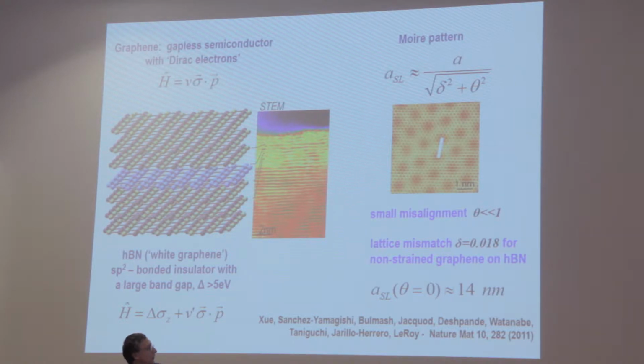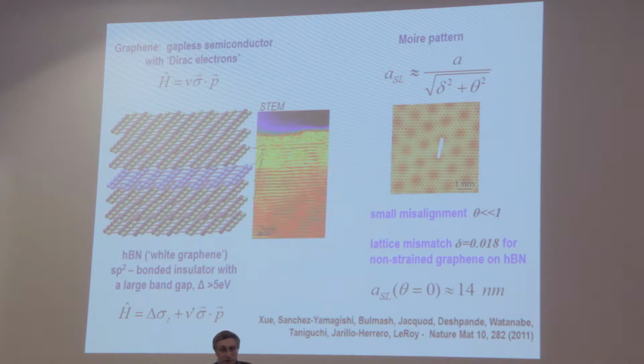Also, I'd like to mention that in the experimental work that exemplifies the structures that I'm talking about, attention is paid to aligning graphene with the underlay of boron nitride. And then the other layer of boron nitride, which is used for protection on the top, is not aligned with the graphene lattice. So that all the Moiré pattern that I'm talking about is coming from one single interface, not being obstructed by possible commensuration between the graphene lattice and the boron nitride lattice on the top.